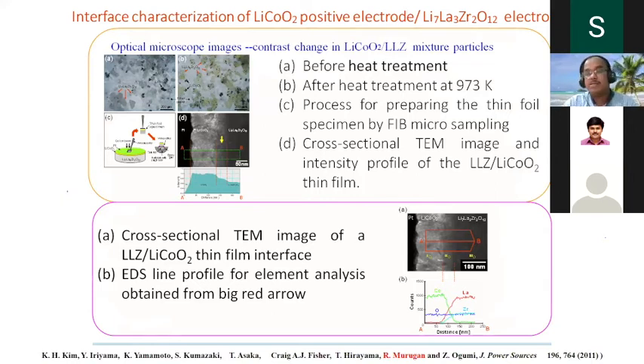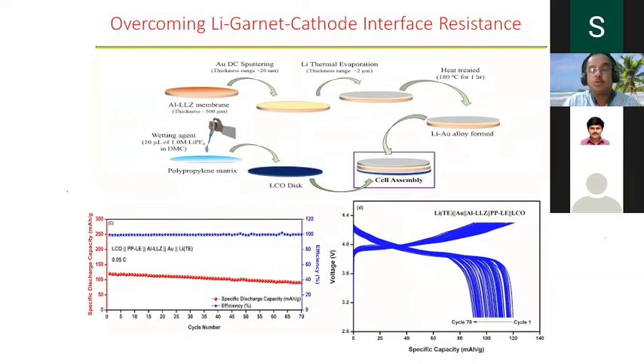What you have is lithium cobalt oxide as a cathode. This cobalt very easily diffuses into the solid. After a few charge-discharge cycles, the cobalt diffused to the lanthanum sites, and what you call a reaction product layer was found here after a few cycles. It starts to give a large interfacial resistance. That's a problem. This is an in situ measurement. We observed that the garnet and lithium cobalt oxide react very easily after a few cycles. Then it forms reaction products that suppress the cycle efficiency. So we realized this should be overcome.